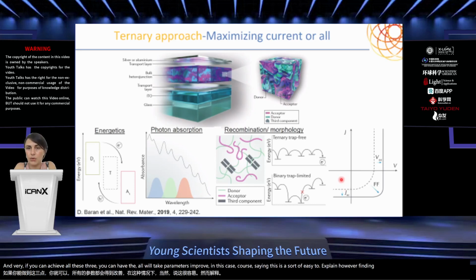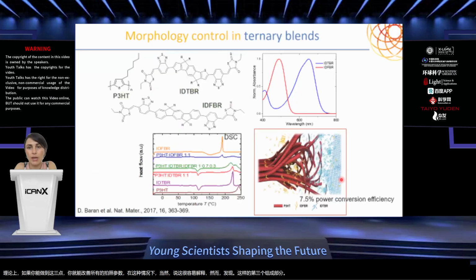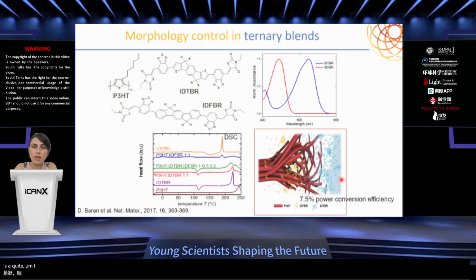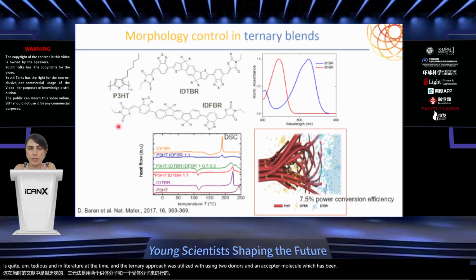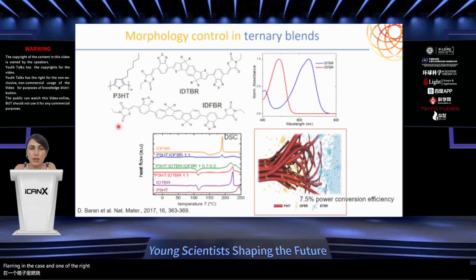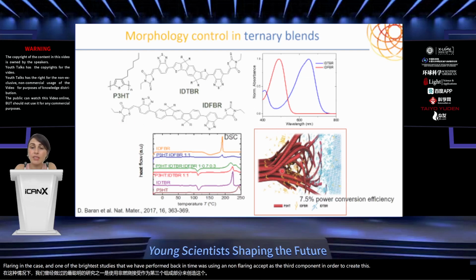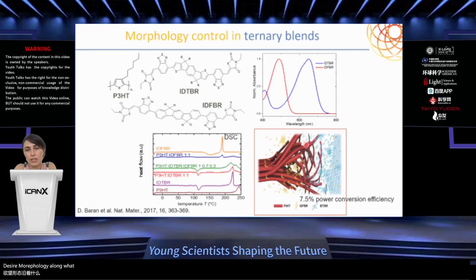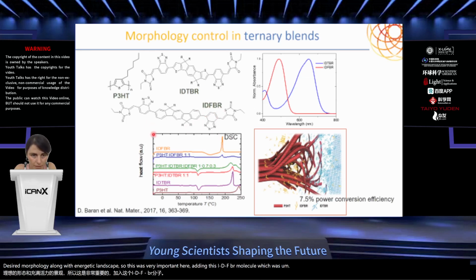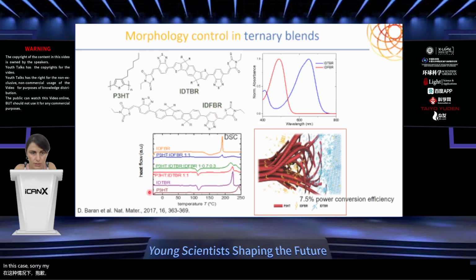However, finding such a third component is quite tedious. In the literature at the time, the ternary approach was utilized with two donors and an acceptor molecule, which was fluorinated. One of the breakthrough studies that we performed back in time was using a non-fluorinated acceptor as a third component in order to create the desired morphology along with the energetic landscape. So this was very important here, adding this IDF-BR molecule, sorry, my screen, I can't hide this,